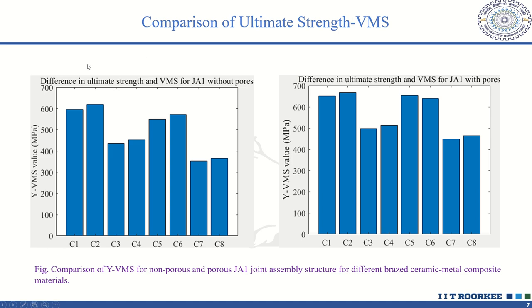And then the comparison between the ultimate tensile strength of different material combinations and the von Mises stress is estimated and plotted. It is found that the difference is highest for the C1 and C2 material combination than the other C3, C4, C5, C6, C7, C8 material combinations. This is because these materials possess the lower von Mises stress, so they can bear thermal stress to higher ranges, and so these can be used for higher temperature applications.